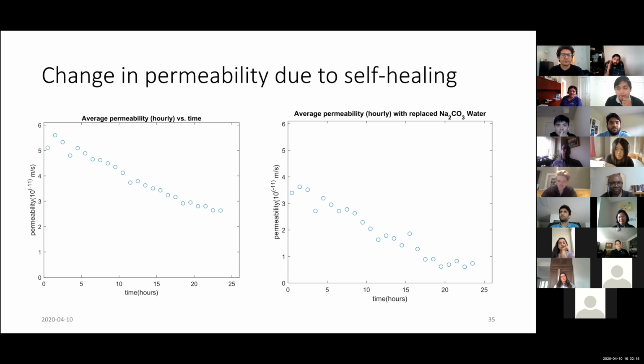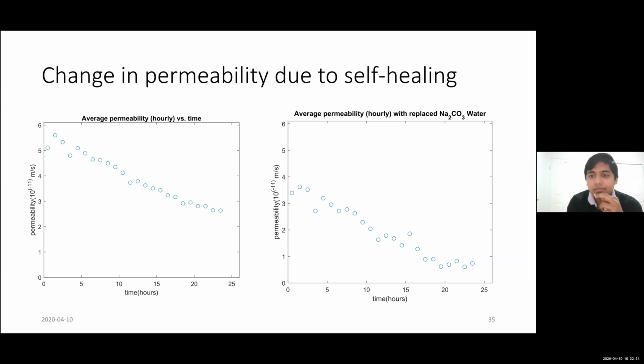So it's about 10 MPa, you said. For a 40 MPa concrete, right? No, the strength of concrete that I tested was around 30 MPa, not 40. So you're just about at the cusp of noticing a change in permeability as a result of stress. Up to 30%, you'll generally see pore compression. As you go from 0% stress to 30% stress, and that's been published by many people, your permeability starts to decrease under that. And then at about 30%, you start to actually see the increase, which you saw as well, right?